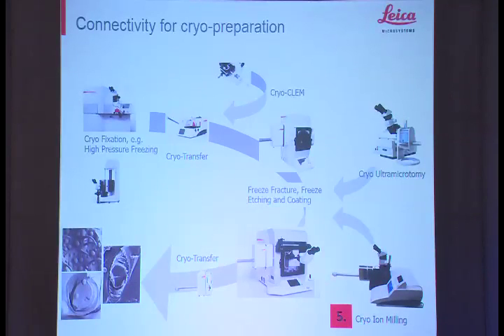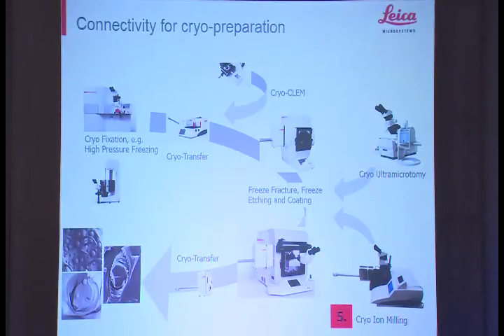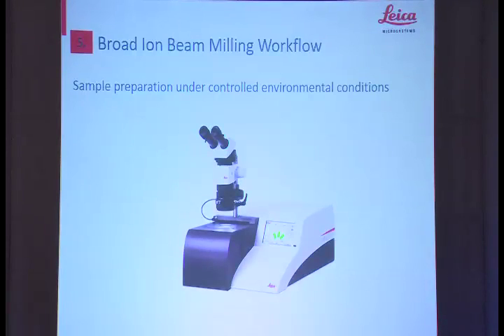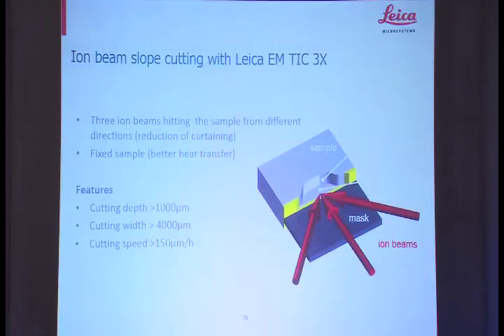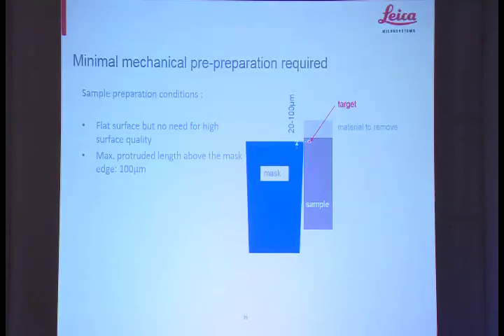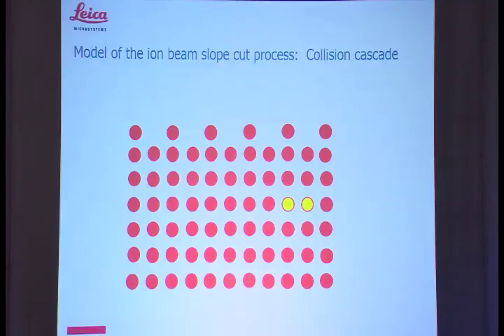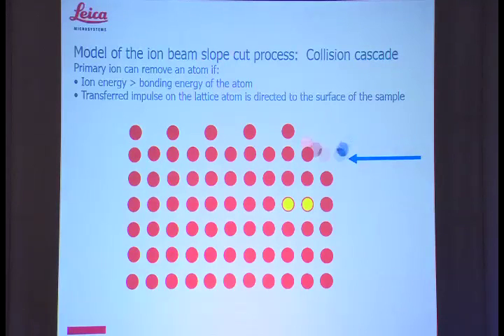So what about this interesting step called cryo ion milling? As a biological technique, it's not really used, because its main use is for industrial sample preparation. So what is it? It's basically a machine with argon guns inside, and you use these argon beams to smooth and flatten a sample. So it's polishing a sample using argon beams. We put a mask in the way of the sample area. This mask protects the rest of the sample from the argon ions, and we use a collision cascade effect to knock out the sample just using the argon ions. And we prepare a very flat and large surface.